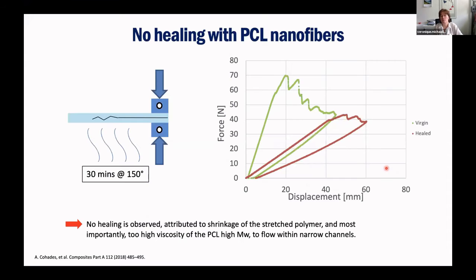But what we saw, which was the downside of it, we have a great toughness. But then we said, okay, let's heal that composite. And 30 minutes at 150 did nothing to it. This is the DCB curve of before, the virgin composite, and then the DCB curve of after. And you see that normally we should expect to go up there again, but we were here, which means that we have zero healing efficiency.